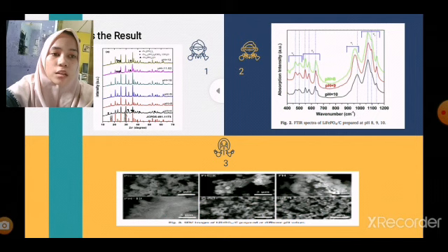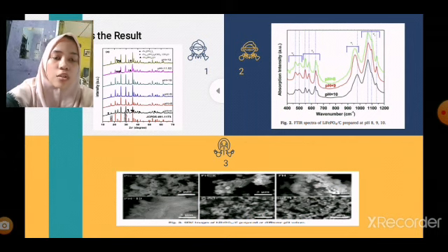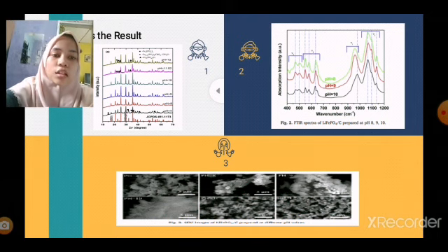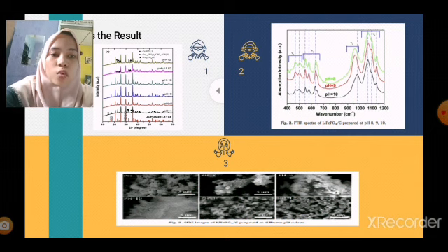This shift is ascribed to the antisite defects. The presence of Fe antisite defects could change the force constants of phosphate groups, thereby enhancing the symmetric stretching V1 mode frequency.